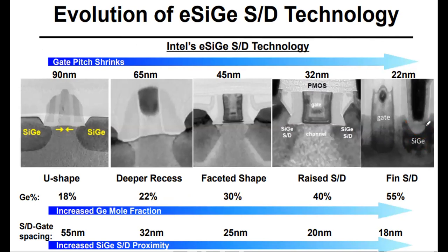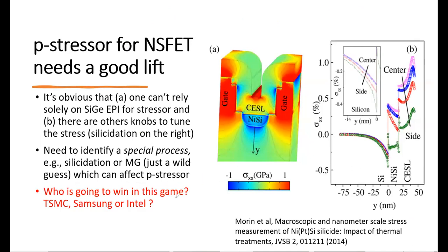And here you need, of course, volume, right? You need a surface area. But at the same time, you reduce the SiGe volume. So the way I see it, the SiGe volume has some effect, but its role may not be as big as before, simply because the amount is less. It's just good and bad, right? You really rely on it to give you strength, but it gives you more variability. So the bottom line is that you need to figure out how to modify or apply processes around this area to give you the strength you want. Is it doable? I think it is.